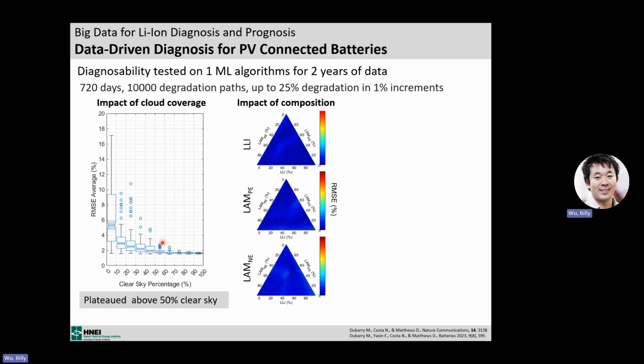And then we can go back to the triangle. And you can see here, it's a boring blue triangle. But that's what we wanted to see. That means the error of our approach is independent of the type of degradation. It works equally for all possible degradation. You can deploy that algorithm without worrying. We prove that whatever the cell degrades, the method works.